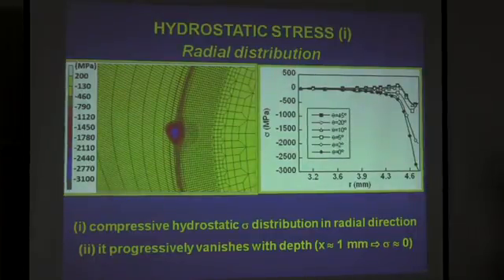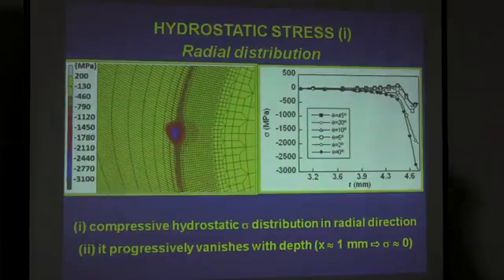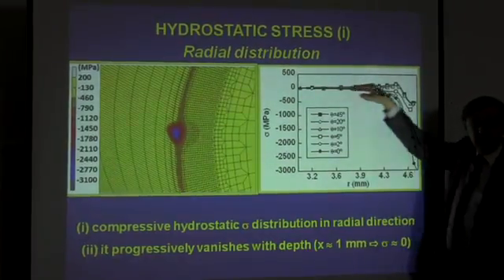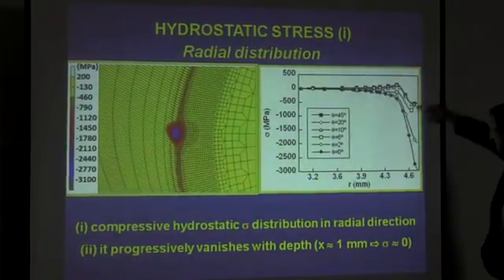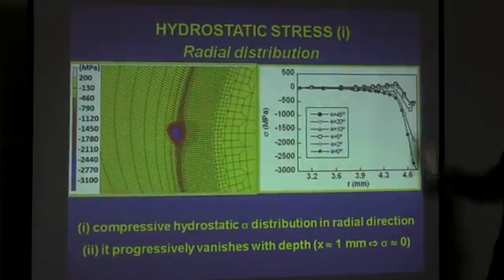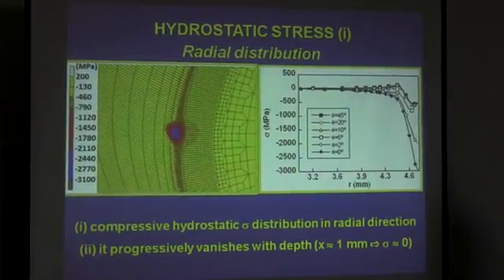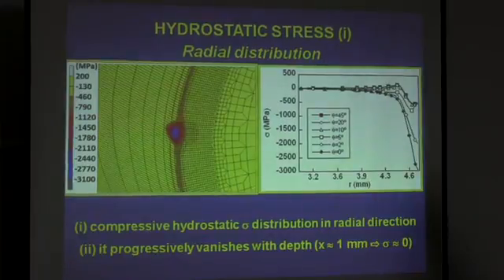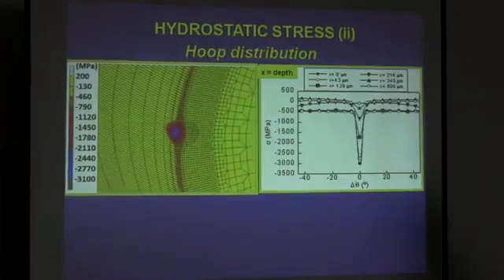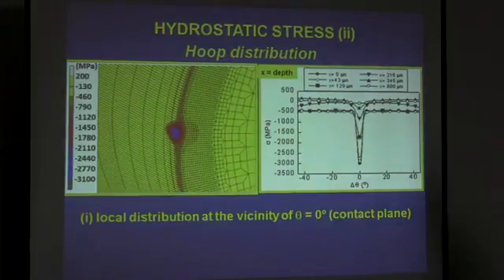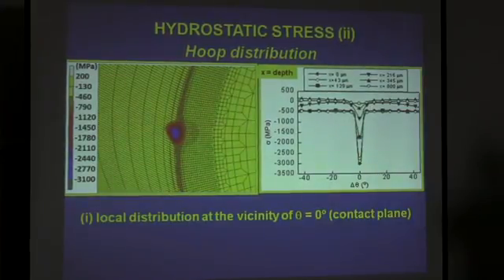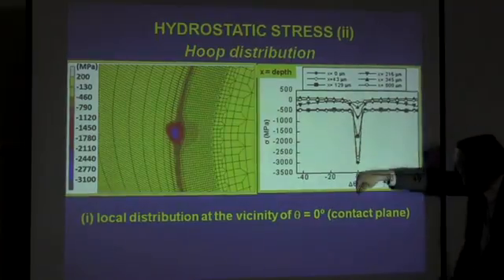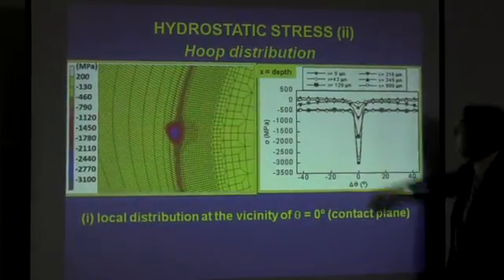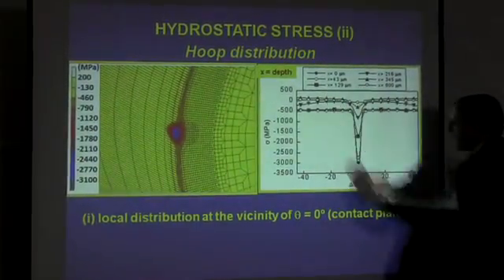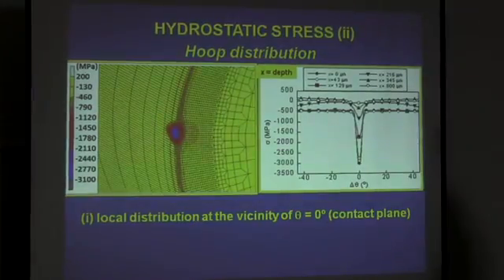It progressively vanishes with depth, approaching zero in the inner points. This is the concentration: negative at the boundary, with positive inward gradients of hydrostatic stress. This is the hydrostatic stress driven component of hydrogen. Regarding the Hoop distribution of hydrostatic stress, again we have a minimum at the contact area, a strong minimum, and a more or less uniform distribution for different angles.